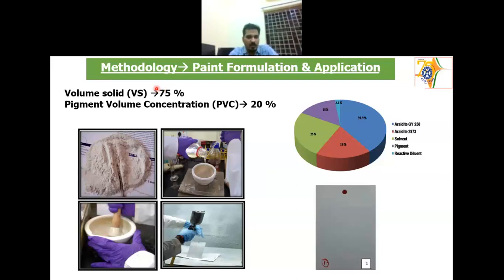And the pigment volume concentration is the concentration of the pigment in the volume solid, that we fix as 20 only. Sometimes you cannot increase it more. At 30, we call it the critical pigment volume concentration. If you surpass the critical pigment volume concentration, the resin, the paint, cannot hold the pigment. It will crack there itself, and then there will not be any barrier property. So we mix the pigment first by adding the resin and the solvents, and then we spray coat it.